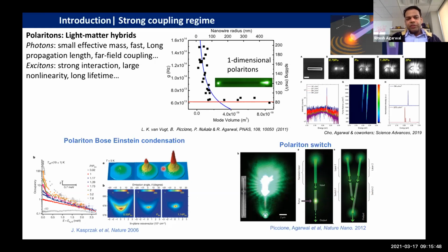But if we reduce the size of the nanowire below a certain size, which again depends on the polaritonic properties of the system, the system suddenly transitioned from a three-dimensional polaritonic regime to a one-dimensional polaritonic regime, where the light-matter coupling strength was a very strong function of the size. So by doing this size-dependent engineering, we basically showed that we can tune the properties of this polariton, and because of these enhanced nonlinearities, we were able to make an all-optical polariton switch by scattering the polaritons in this one-dimensional channel.